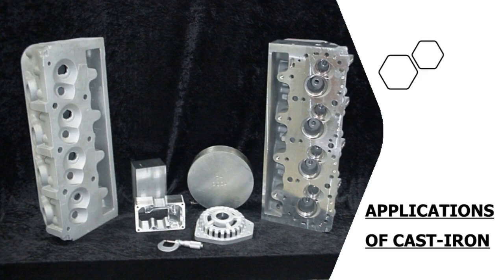When machining cast iron, your first roughing cut should penetrate the hard abrasive outer skin of the casting to preserve tool life. Care should be taken when threading cast iron to prevent crumbling of the threads. Light cuts normally ensure a good thread.